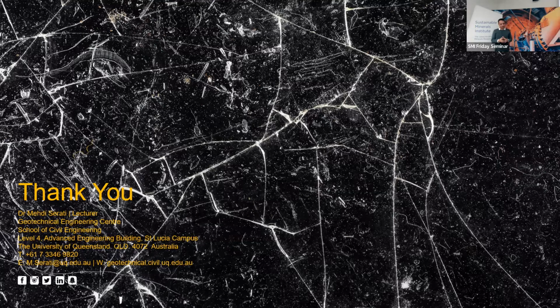Yes, good question, because I remember for this ceramic we were using Macor, that's a brand name, Macor glass ceramic, and we ordered a UCS sample from the UK, and we couldn't manage to break it with any load frame available at UQ. Then we looked at JK. You used to have a very big machine, and I don't know if it's in operation since the old times when Eric was the lab manager. We could manage to break it, but then the thing is, it's a big system. How is the stiffness going to affect it? Because these types of huge machines are usually for big sizes, and this sample is small.